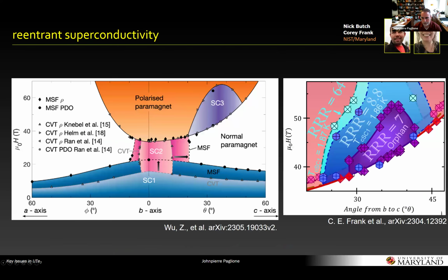And it's been shown that this also survives as you increase the base TC. So increasing the base TC with salt flux crystals increases the upper critical field of the low field phase and widens this phase as well. And you can see that this SC3 phase seems to be still consistent here. Okay, so let me see here.